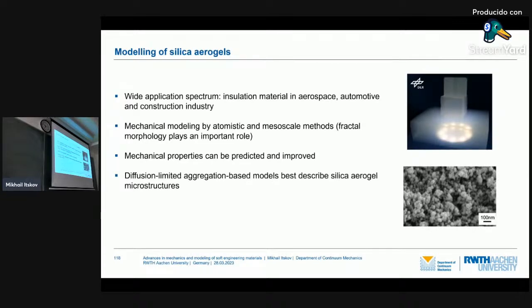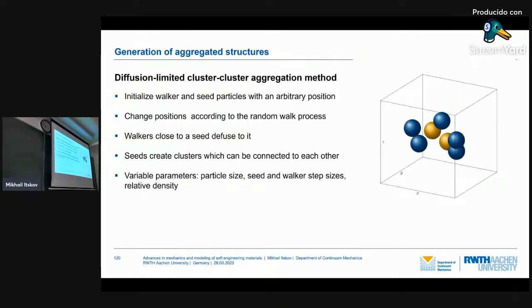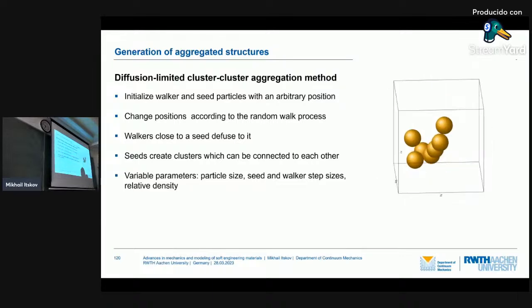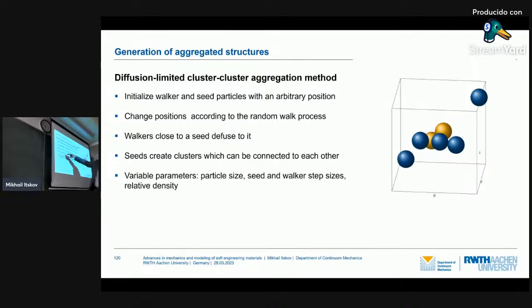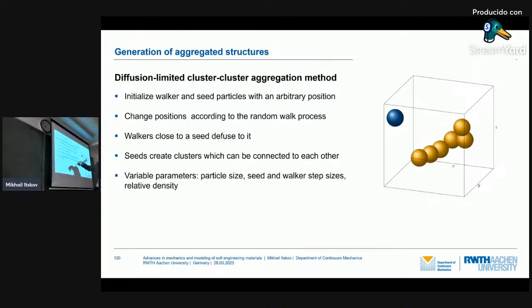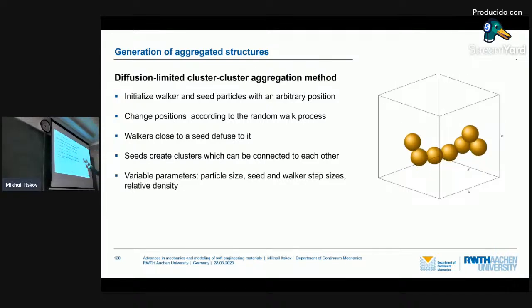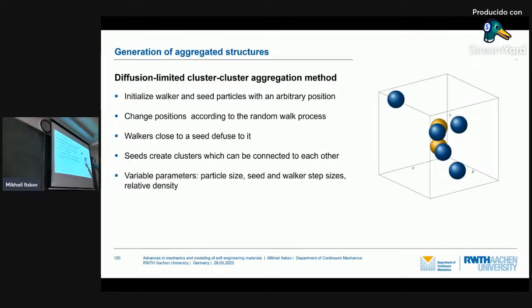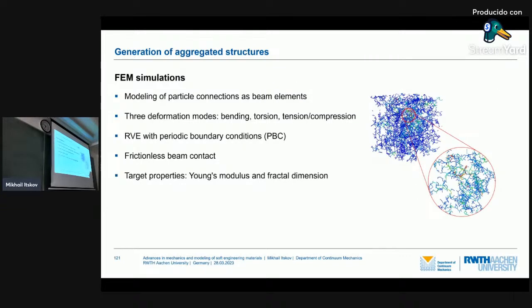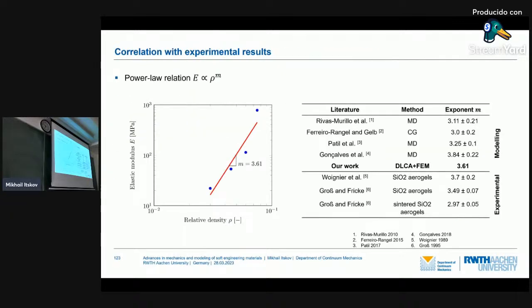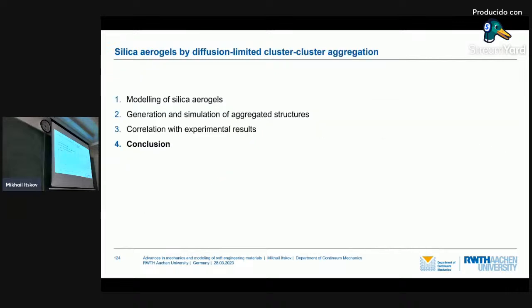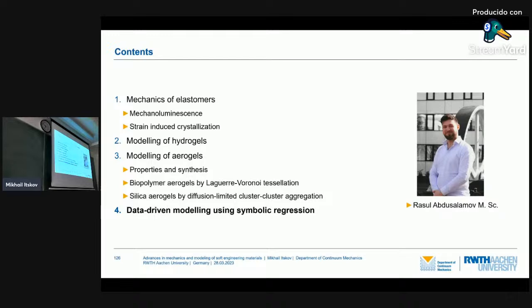This is silica aerogels. And the idea is to use this diffusion limited cluster aggregation. We put some seeds and some walkers, and these walkers randomly walk around the seeds, and when they come closer, they connect to them and begin to form these aggregates, right? That's the idea of this model. We see here the results of this model. We also apply here finite elements with RVEs and periodic boundary conditions, and also here we have rather good agreement. For example, again for this power law expression.